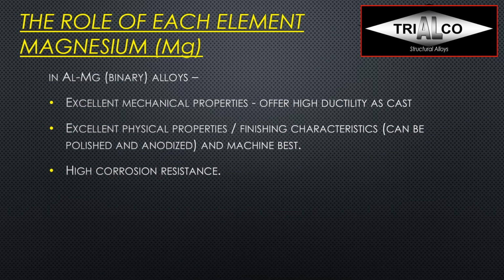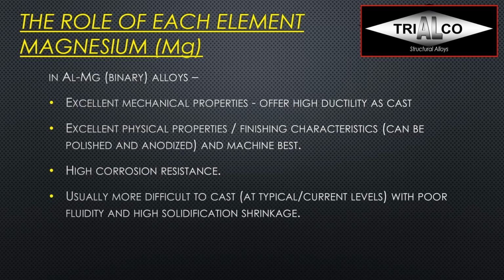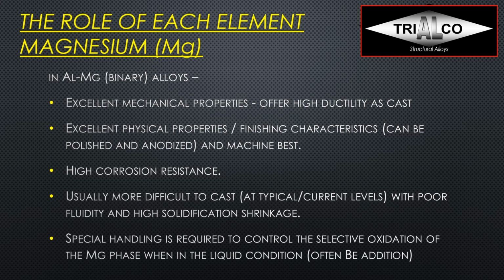They show excellent corrosion resistance, and usually it's more difficult to cast than any 300 or even the 400 series alloys, at least at the typical current levels. Relatively poor fluidity and high solidification shrinkage. We also need special handling and have to control the selective oxidation of the magnesium phase when in the liquid condition. So therefore, very often beryllium is added into these alloys.